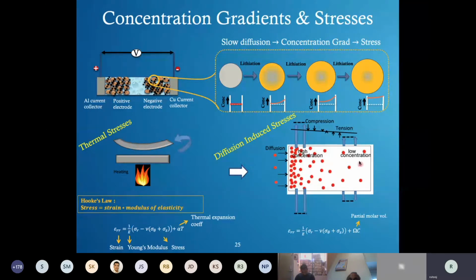But to maintain the continuity of the surface, there would be a compression on the outer surface, and there would be a tension on the inner surface. So there are these stresses happening, and these are diffusion-induced stresses. And then you can calculate how much the diffusion-induced stress would be when you are charging and discharging your battery at a particular rate. Again, the higher the rate, the higher these stresses would be.